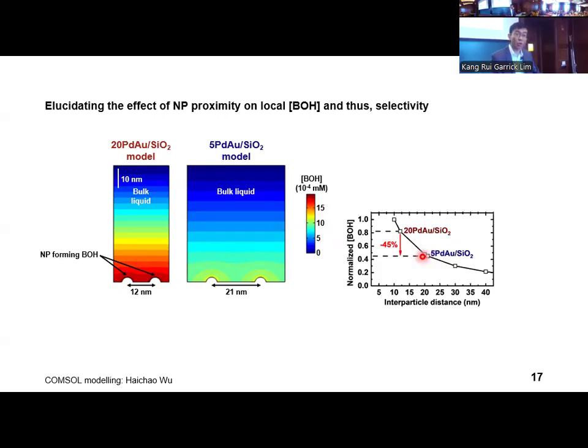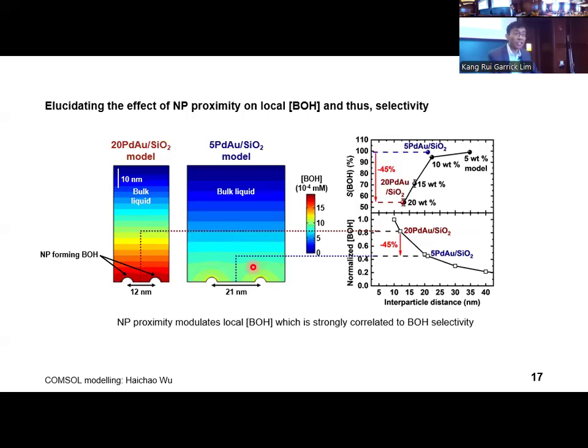As the 5% catalysts show a local benzyl alcohol concentration about half that of the 20% catalyst, which you can see by comparing this point to this point, the likelihood of benzyl alcohol readsorption on the 5% catalyst is greatly reduced, thereby minimizing toluene production and increasing benzyl alcohol yield. This conclusion agrees with our experimental data, which indicate a substantial enhancement in the selectivity towards benzyl alcohol from 54 to 99% as the average interparticle distance increases from 12 to 21 nanometers. The benzyl alcohol selectivity trend at different interparticle distances also depicts a negative relationship to the local benzyl alcohol concentration trend, underscoring the strong correlation between nanoparticle proximity and product selectivity.